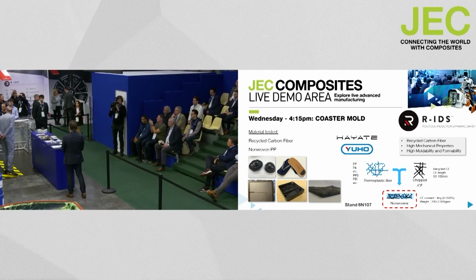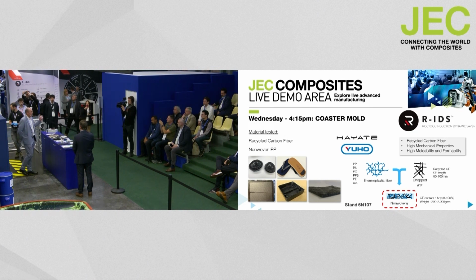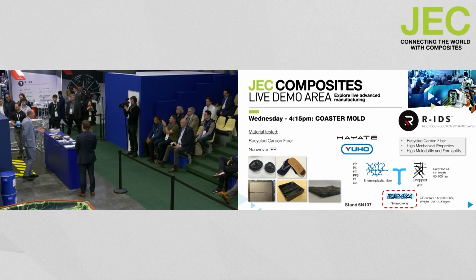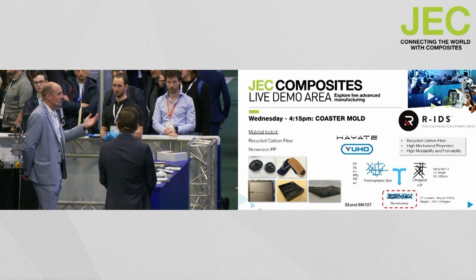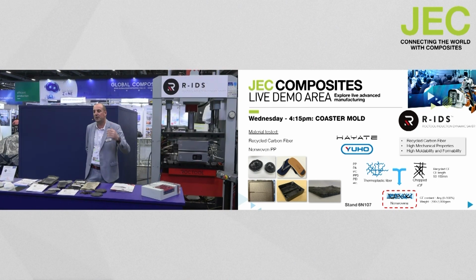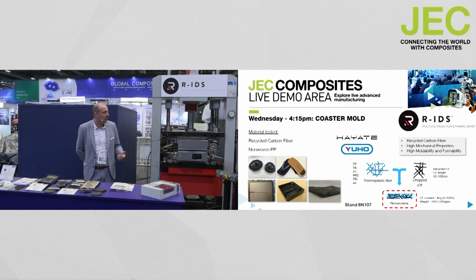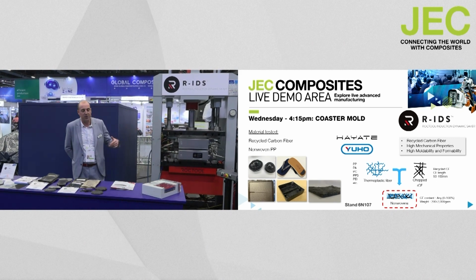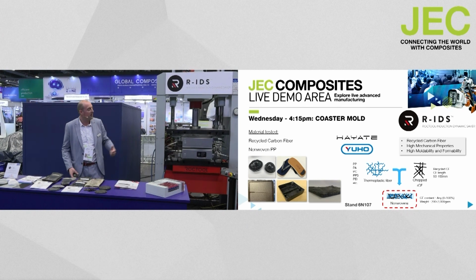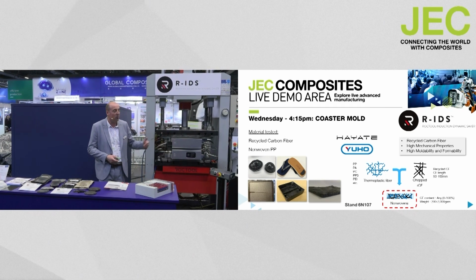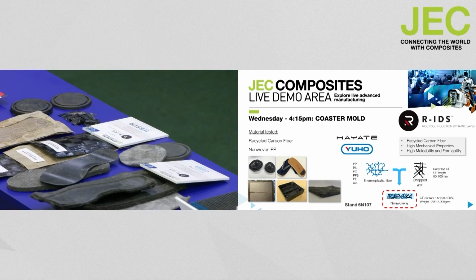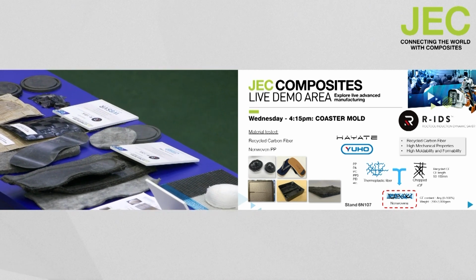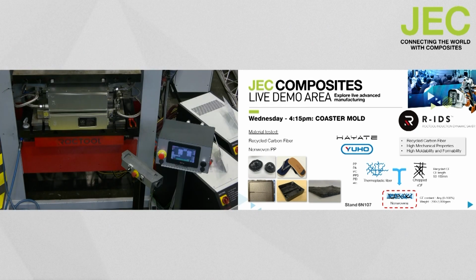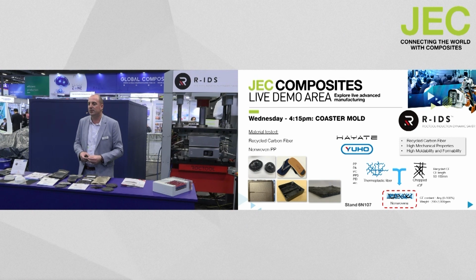So we have again a few seconds before we start the cooling. Due to the material, we don't need to spend a lot of time at constant temperature. We melt the polypropylene. We apply the pressure to consolidate the material in the cavity. And so immediately now we can stop the heating. As soon as we stop the heating, we stop the energy consumption for the heating, and we start to cool. We push the water inside the circuit to quickly reduce the temperature.